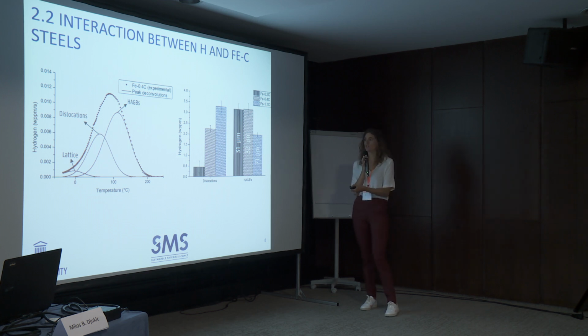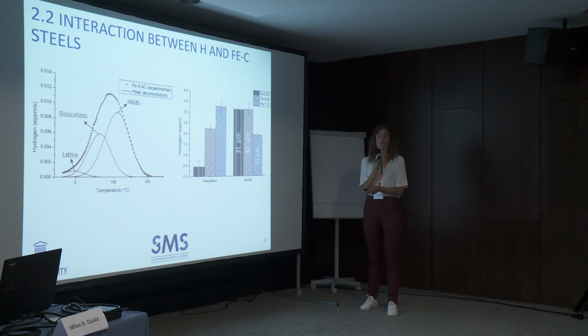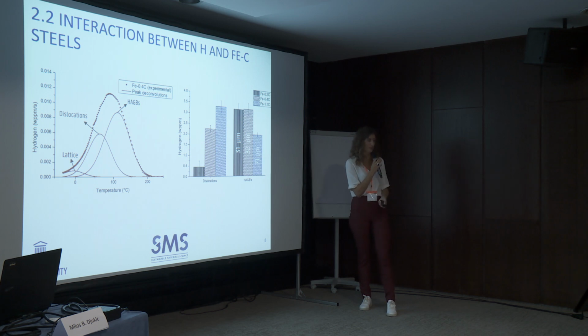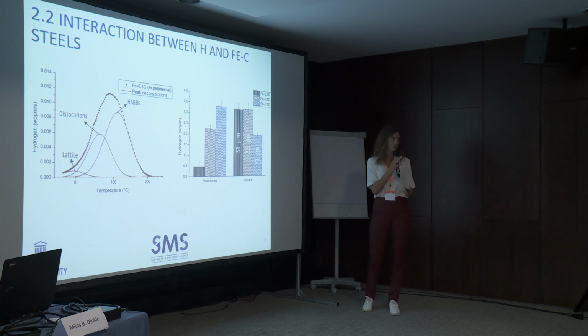The amount of hydrogen trapped at the trapping sites is calculated as the area underneath the Gaussian curves, which correspond with that specific trapping site. So what do we see? Well, the amount of hydrogen trapped at these locations increases with increasing carbon content. This is, of course, because carbon in solid solution induces more dislocations, so we have more available dislocations as trapping sites.